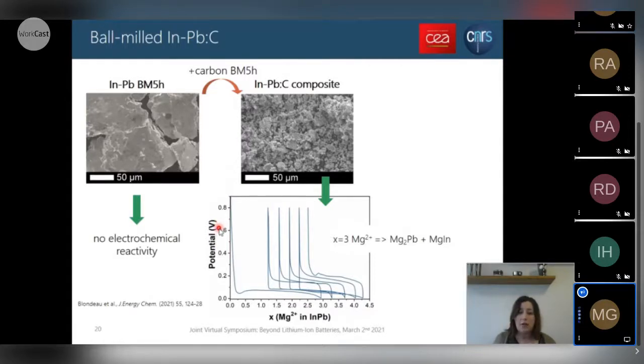When you look at the evolution of the potential as a function of the magnesium inserted in this structure, we can see that in the first magnesiation we can get close to 3 Mg2+ inserted in the structure, which is in fact expected if we take into account the formation of Mg2Pb and MgIn phases upon reaction with magnesium.